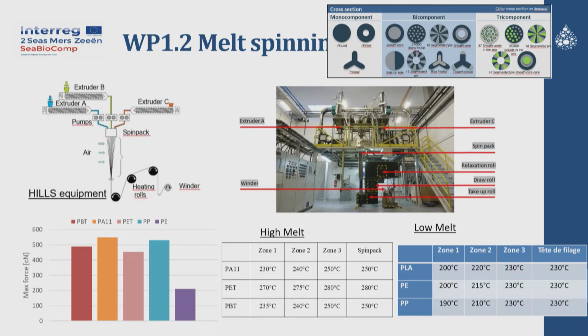Firstly, we tested several polymers, which could be bio-sourced or not. What came out of this study in melt spinning is polyamide 11. If we talk about high melt polymer, polyamide 11 seems to be the best solution in terms of tenacity. PLA was quite difficult to process. But PLA, of course, is quite compatible with natural fiber, so you will see after that in a different process it will be better.